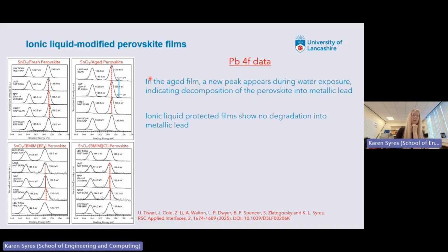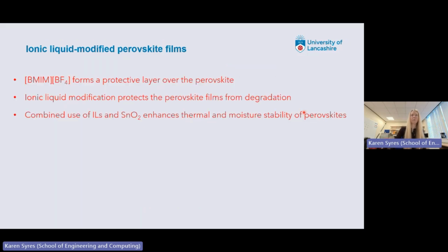But our ionic liquids are fine. We don't see any degradation of the perovskite when it's mixed with the ionic liquid. So again, it's showing that this does protect the films.